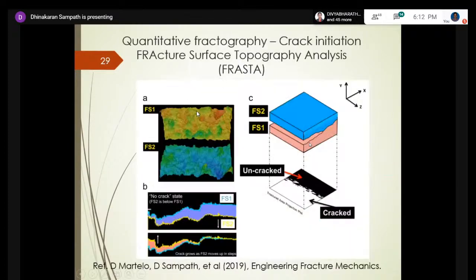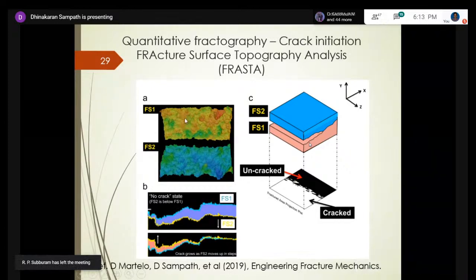So here comes the quantitative fractography, crack initiation. We are going to find the crack initiation point using fracture surface topography analysis. This is the main bit of this study. This was done in the 90s. They used surface topography to replay or reenact the fracture event. So what we did was take the topography of the fractured surface, the complementing surfaces, and fix one surface, and then pull one below that, so that it simulates the no-crack state.